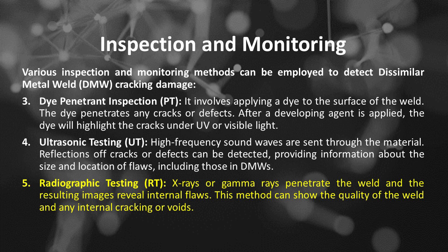Number 5 is radiographic testing, or RT. X-rays or gamma rays penetrate the weld and the resulting images reveal internal flaws. This method can show the quality of the weld and any internal cracking or voids.